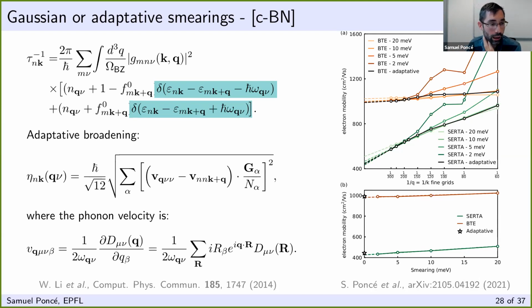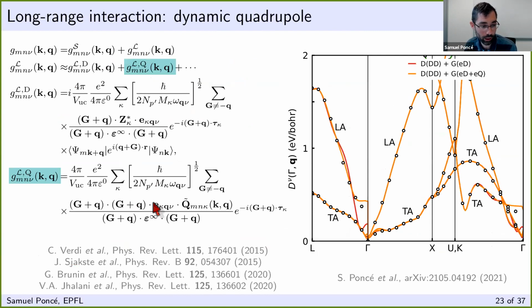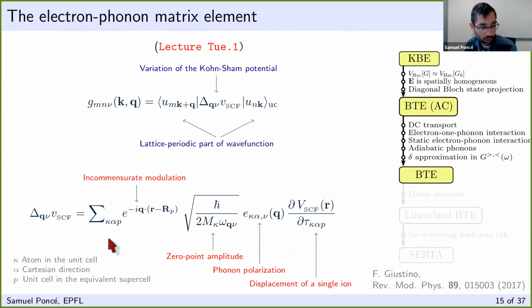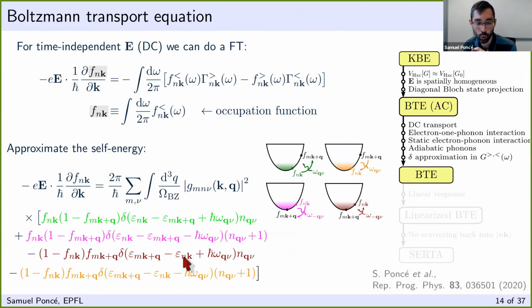And so the new physics, I mean, in the end, you could obtain from a semi-empirical argument something similar indeed to this equation here. So I don't think in that regard you have new physics, but the advantage of doing this derivation is that now we have very well-defined approximations. And therefore, we can try to look at which ones we could remove to move towards a more accurate equation, which I think was not possible from an empirical or semi-empirical derivation.